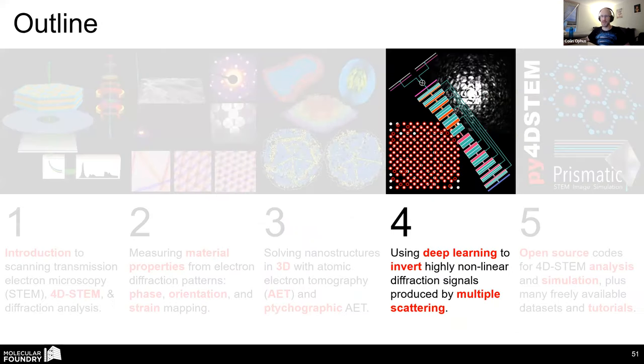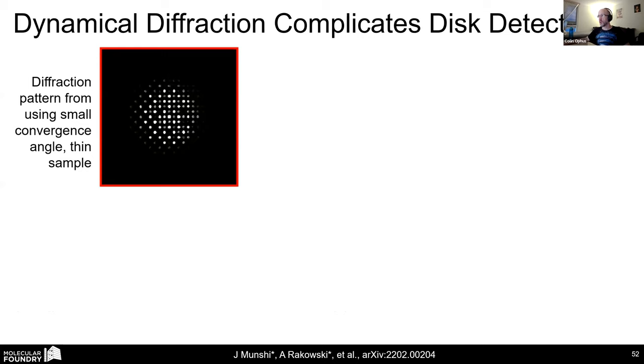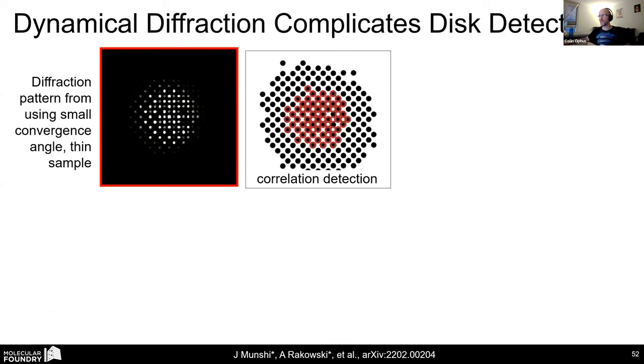Okay, so in the last couple of minutes of my talk, I just want to show you where we're going with these analysis methods. A lot of our diffraction patterns look really clean, and you can identify all the circular Bragg diffracted disks and then use conventional correlation disk detection to measure all the spot locations. This is a simulated data set, so black is the ground truth and red are all of the determined positions.